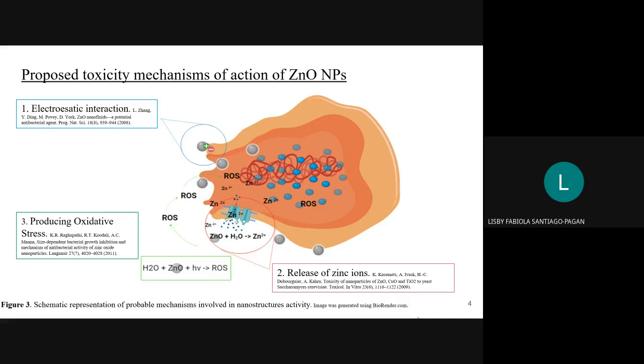The second mechanism is through the release of zinc ions. Kasemets and co-workers propose that toxicity of zinc oxide nanoparticles is directly proportional to the solubility of zinc ions in the medium. Zinc ions have been shown to negatively impact active transport enzyme systems and can interact with other species, causing disruption of the cellular environment. However, this proposed mechanism is limited in that the dissolution of zinc ions from zinc oxide is dependent on many variables such as pH, particle size, other components of the medium, exposure time, among others.